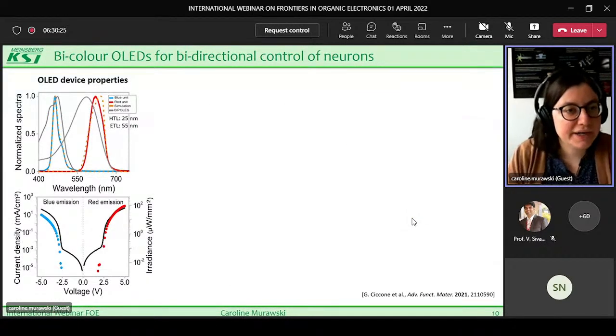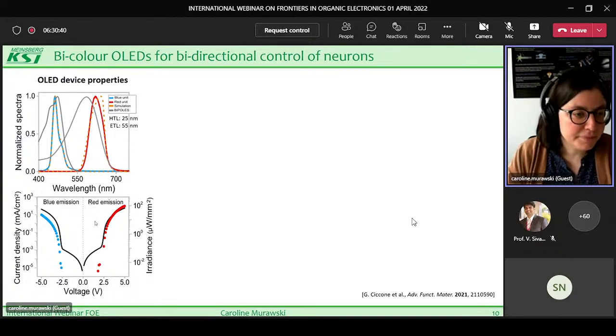So in our actual devices, the spectrum was matched quite well compared to the simulation. So we have the simulation here in orange, and the red and the blue are the experimental spectra of the devices. And if we now look at the performance of these devices, this is shown here in this graph. We have the black lines showing the current density, and you see that when applying forward bias, we have red emission, and if we apply negative bias, we have blue emission.